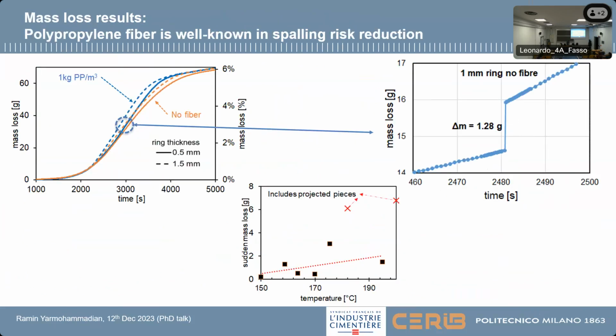So for the mass loss result, I would say it is known that if we use polypropylene fiber, or PP fiber, we're gonna get less spalling risk. So why is this happening? For example, you can see in some samples, if we use PP fibers inside concrete, the concrete is gonna be drier. So if we have drier concrete, we do not have water which can convert the thermal energy for us. And another point here is if the spalling happens later, which is at a higher temperature, the sudden mass loss, which is inside the spalling, is higher.